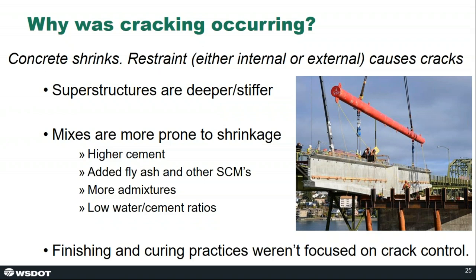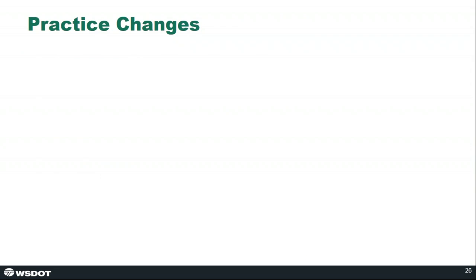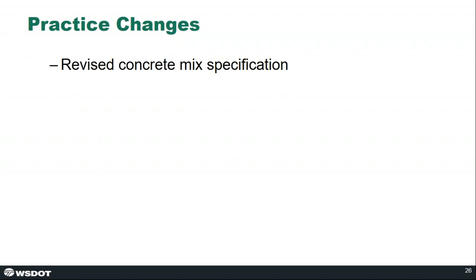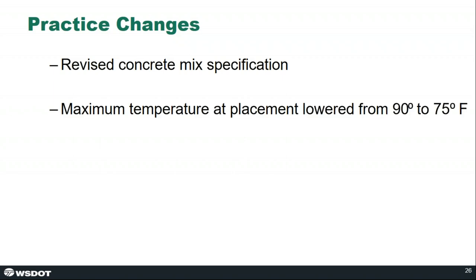And lastly, our finishing and curing practices weren't necessarily focused on crack control. And that's something we've addressed as well. So just to summarize some of the changes that we underwent about 5 to 7 years ago, we revised our mix specification to the performance-based spec that I covered. We reduced the maximum temperature at placement from 90 degrees to 75 degrees to ensure that the concrete is going to stay workable and finishable and can be appropriately cured.